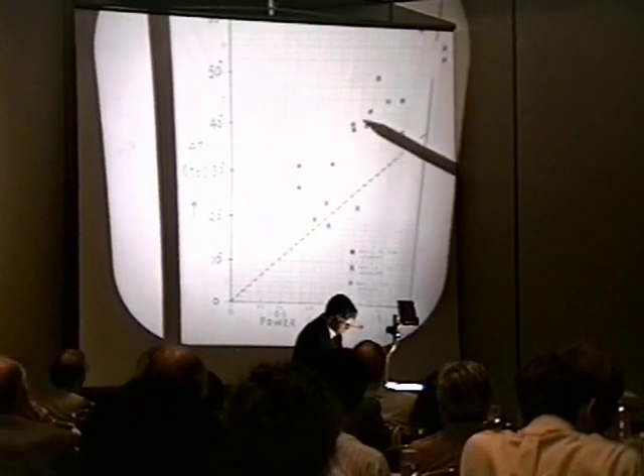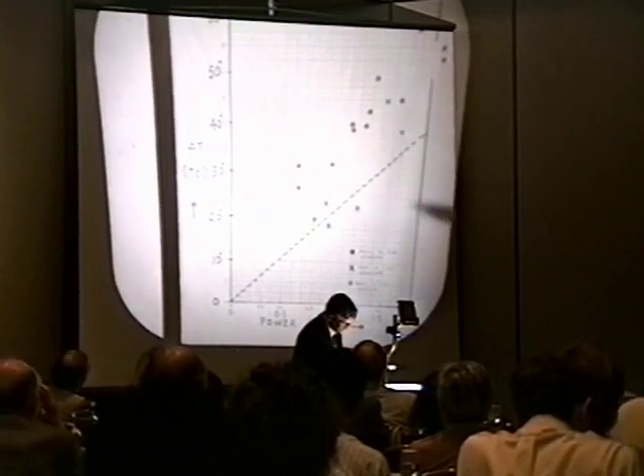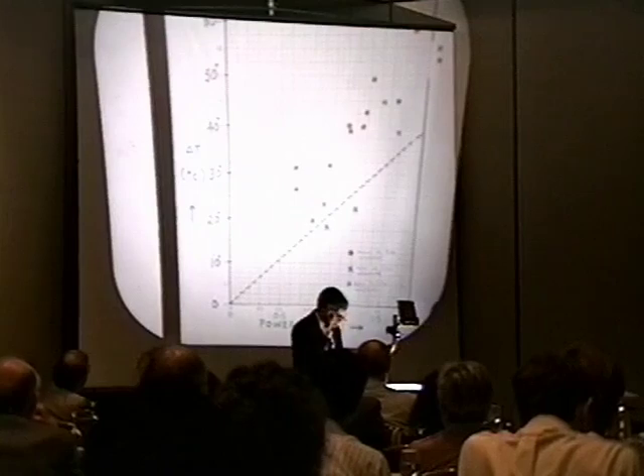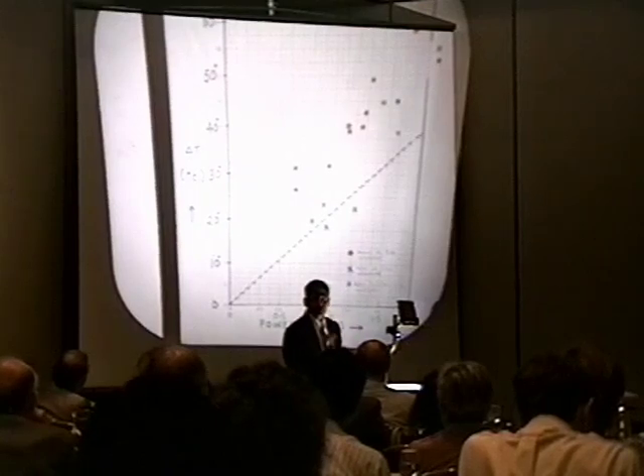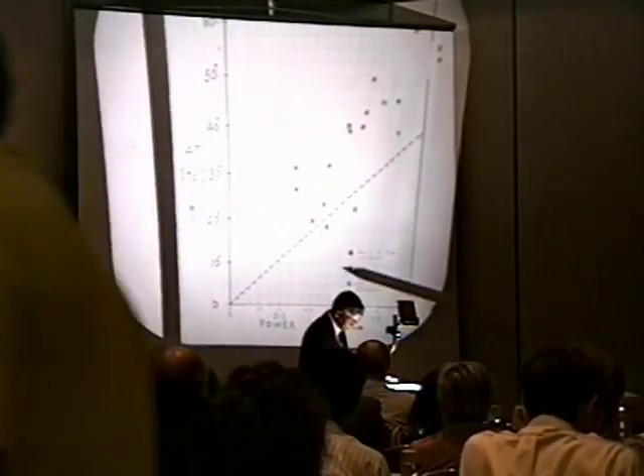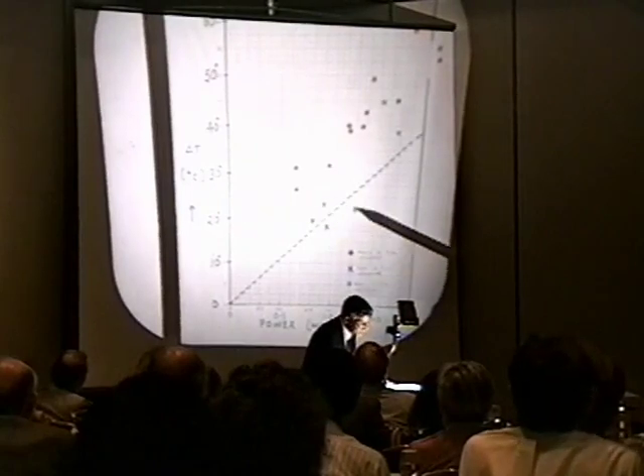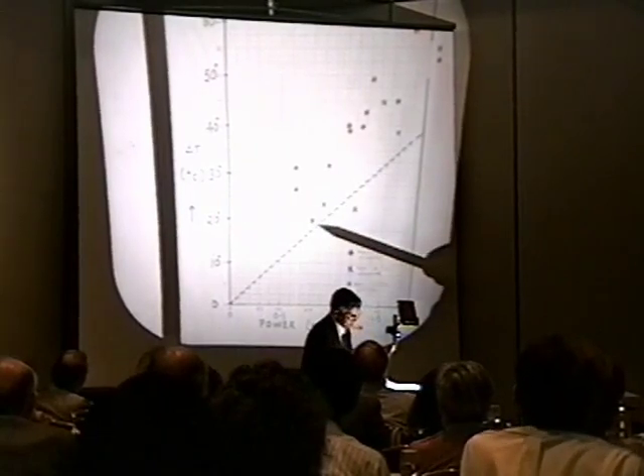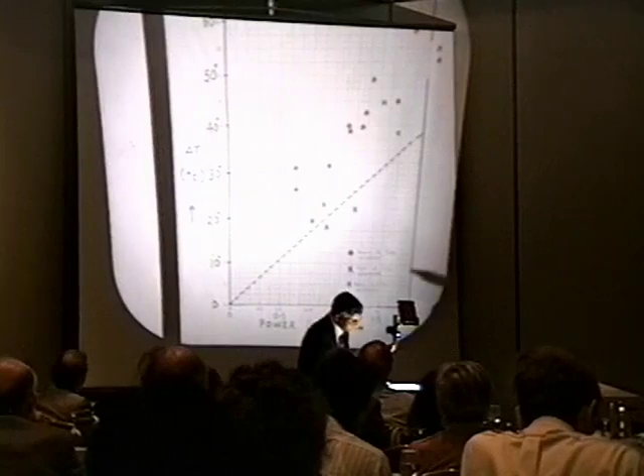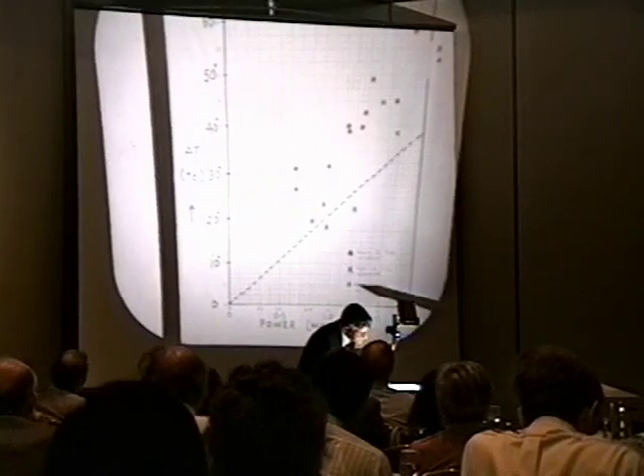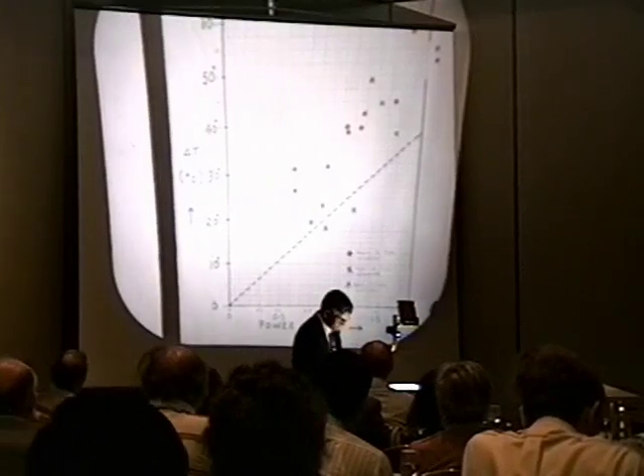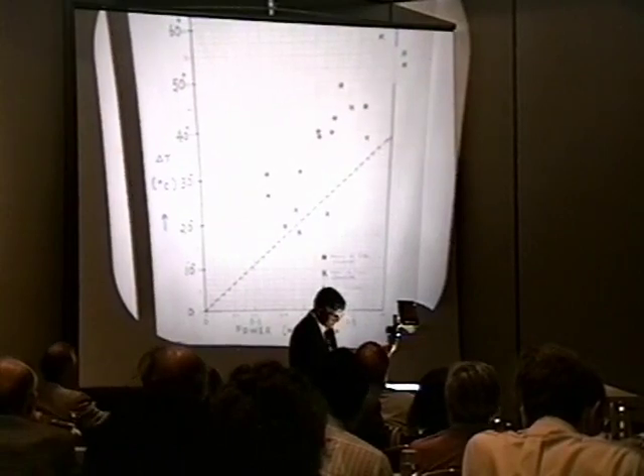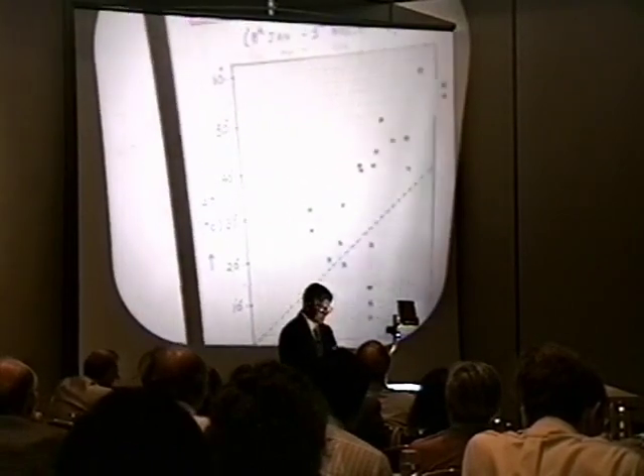Now I'm going to show you the same XF2, same results, plotted with slightly different conditions. These are the initial points which showed us excess heat. What we did in this was introduce a stainless steel rod into the system. It was working, no other change, and these are the blue points. The excess heat vanished altogether. At this point, we took out the stainless steel rod and the stainless steel tube and changed the solution, and once again we started seeing the excess heat. So this is how we learned to avoid stainless steel in our cells.